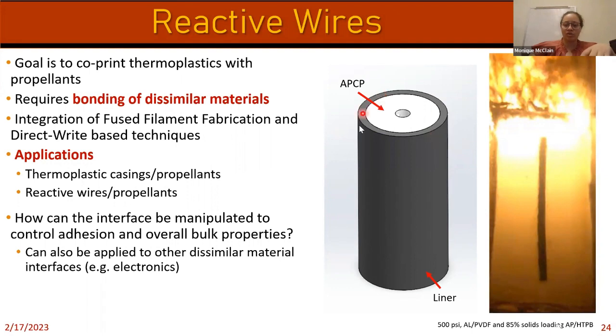Typically you want to make sure that, when you're bonding this propellant to that liner, there's no delamination between those two layers. Because if you have delamination, your propellant flame can spread through the interface, which could blow apart your propellant chunks and possibly your motor. So one advantage: could we co-print the liner with the propellant grain as we go? Not only can we potentially have more control over the adhesion, but we can monitor, okay, is this bonding or not?